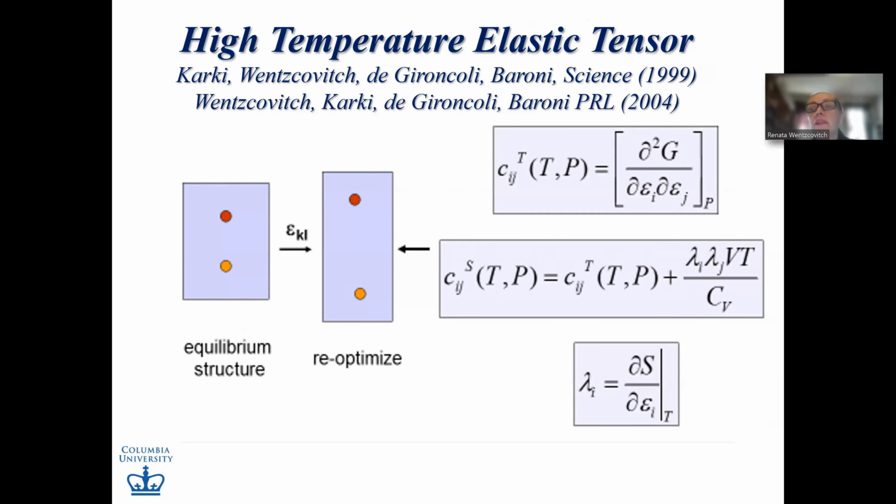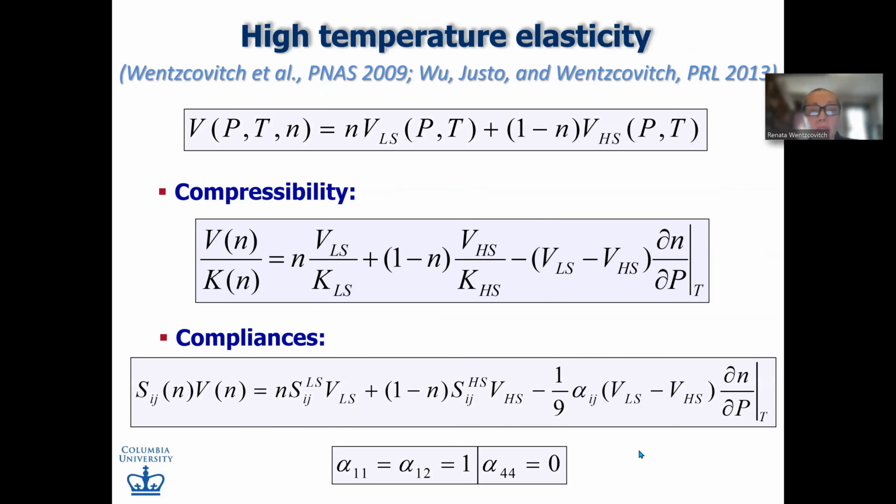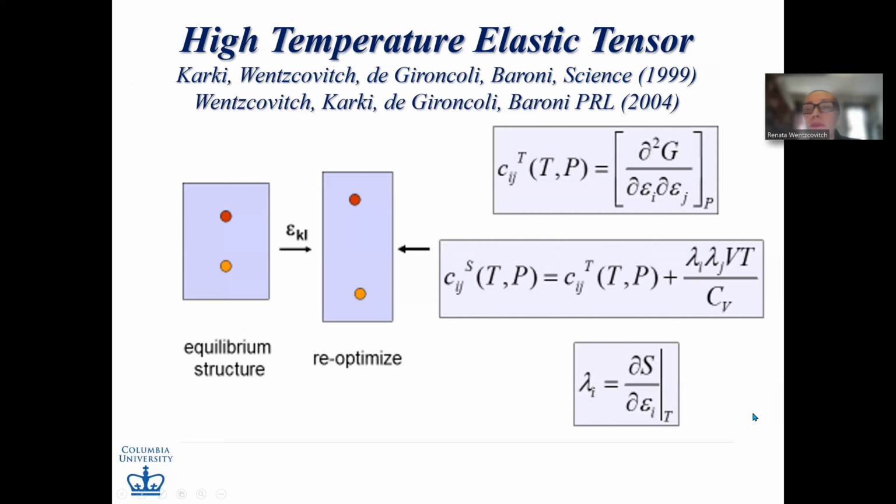And the interesting thing is, you only need to calculate these elastic coefficients, Sij or compliance coefficients, for the end members, not for the real solid solution. So how do you calculate elastic coefficients for end members? That's how we have always done it.